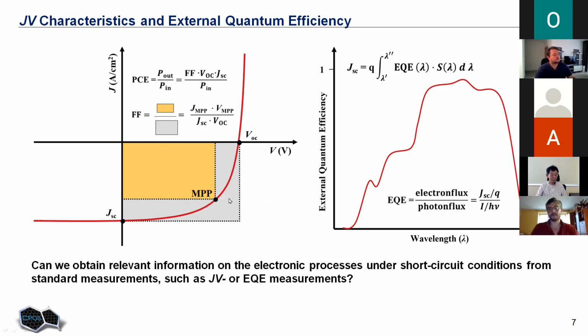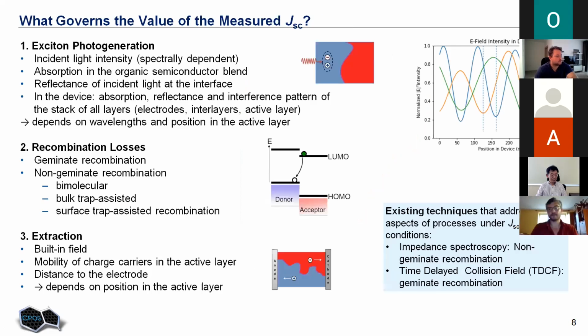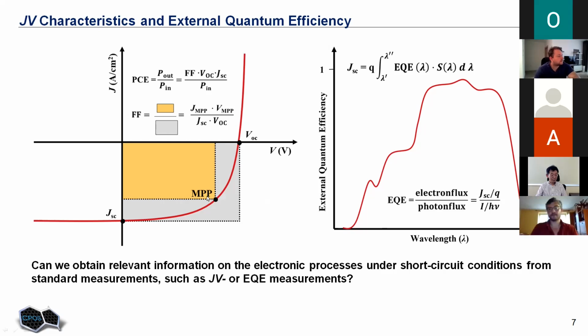And also we have this fill factor, which shows how close the JV curve is to this ideal rectangular. So we would like to have something like this rectangular. However, in real life, this shape is not so nice, and that's why we need to take into account fill factor, which is technically the ratio of this area which we get at maximum power point. So it's maximum power which we can extract from the solar cell, divided by the product of short circuit current and VOC. So this gives us fill factor.